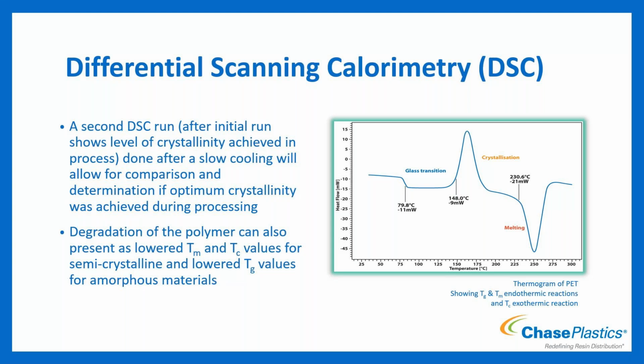The other thing that it can show, if you know where to look or you know those particular thermal transition points for those materials, if you're starting to degrade the material, whether it be during processing or wherever it had occurred, what you're going to find is when you do the DSC, you're going to see a lower TM, a lower TC for your semi-crystalline materials. So if we were to go back to the nylon one where it had that peak down at 260, it would be a lower value. So maybe it would start in the 240s, 250s. And so it's a lowered value. And then for amorphous, similar, but with the TG value. And so you would see that it would be lowered because it's being degraded.